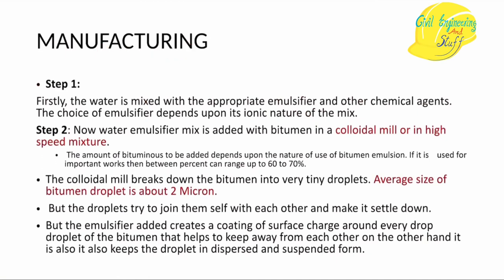In the manufacturing process of emulsion, the first stage is that water is mixed with the emulsifier. The choice of emulsifier is based upon the ionic nature of the overall mix and the type of bitumen used. This water-emulsifier combination is then added with bitumen in a colloidal mill or high-speed mixer, rotated at very high speed. At this high speed, bitumen particles break apart, the emulsifier forms a coating around each particle, and the bitumen is present in water in a suspended stage.